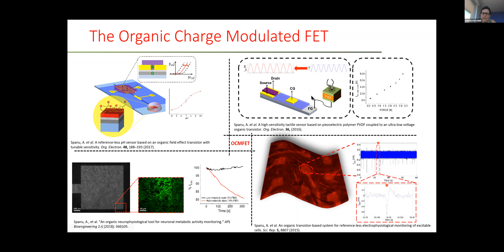We were also able to measure physical parameters by connecting the floating gate area to a capacitor whose dielectric layer is a piezoelectric polymer, able to modify the charge according to the pressure exerted on it. The approach we followed for realizing this example of electronic skin uses this principle: we put on the sensing area of the device a layer of PVDF — a piezo and also pyroelectric polymer that can be deposited by spin coating or inkjet printing, techniques that can be quite easily upscaled.